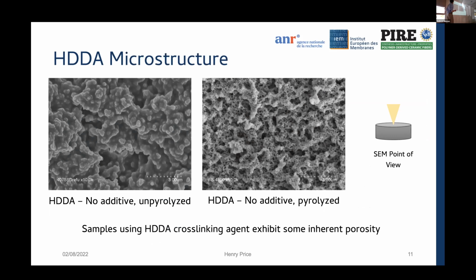Now a bit on the microstructure. This is a view of the top of one of the samples with no additives post pyrolysis. As you can see, it's quite a rough surface with potentially some inherent porosity. So this would be porosity without any additives for induced porosity. This is an interesting finding, and I believe this is one of the reasons why there was such prevalence of that delamination, that mechanical cracking, because there's a large amount of porosity, meaning a large amount of gas needs to go somewhere.